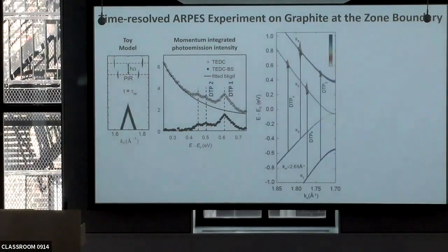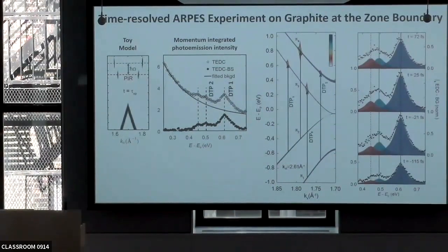Why all these peaks? Well, in fact, if you look at graphite, it has a more complex band structure than graphene, so there are many more optical transitions which are allowed. There are in fact 4, and in this particular range, there will be 3 optical transitions you should be able to see. So we're concentrating now on 2 of them, which match exactly what you would expect here. And what we do next is, here in blue, we show the primary peak, the strongest one, and the second one in blue, the ones that we know. And then we concentrate particularly on the red one, which does not match any of the optically allowed transitions, in the hope that maybe that would relate to a phonon excitation.